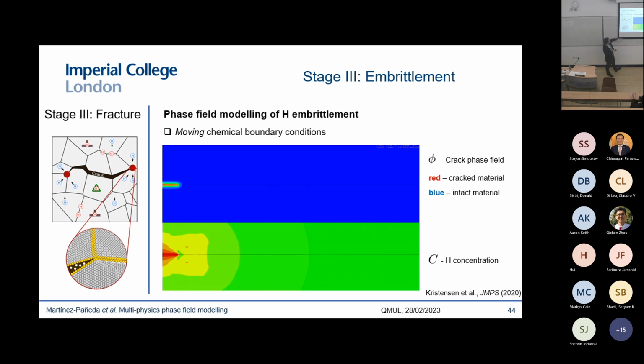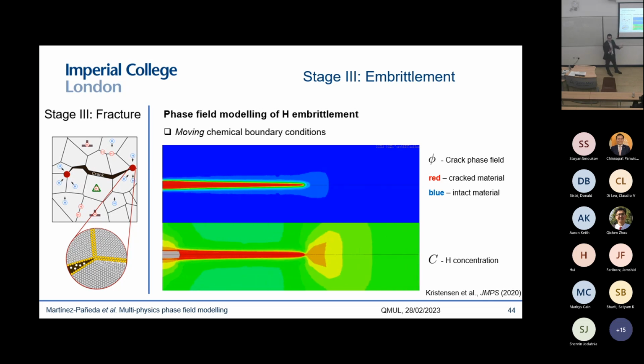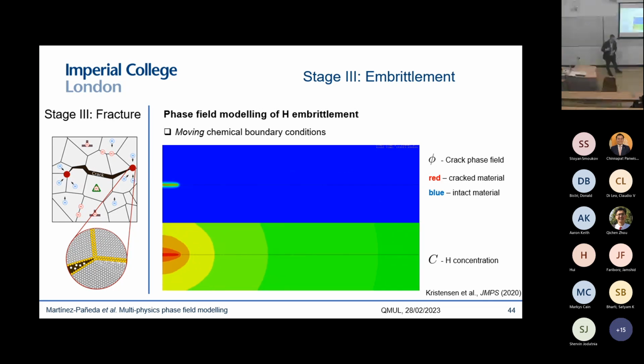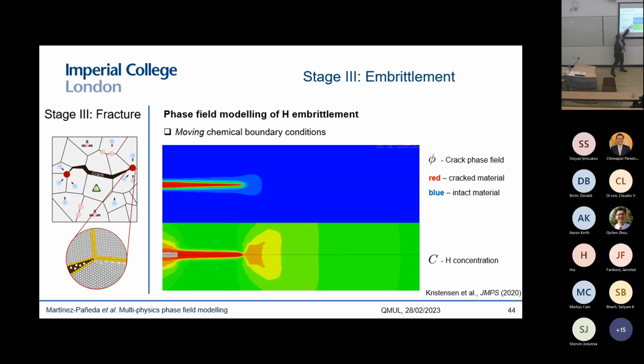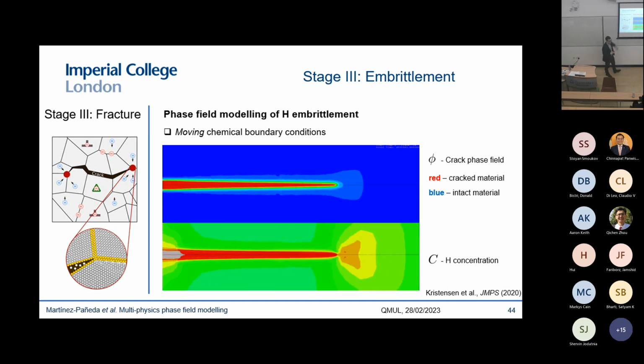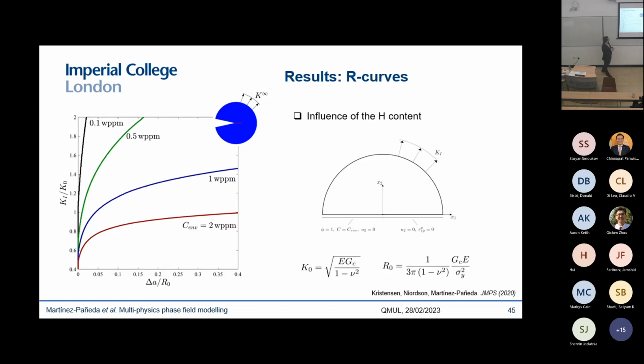And before I do so, let me also emphasize that we're not only interested in the nucleation of cracks, we're also interested in subcritical crack growth. So we want to model, as you can see in the slide, how whenever a crack is propagating, if our sample is exposed to a hydrogen-containing environment, the environment is going to follow readily. So if you have, for example, a pipeline in the middle of the sea, the moment the crack propagates, these newly created crack surfaces are going to be immediately exposed to the source of hydrogen that is, in this case, the sea. And you can see that we can capture that easily with a penalty approach, and there's many other approaches that we can use. But let me show you some results.